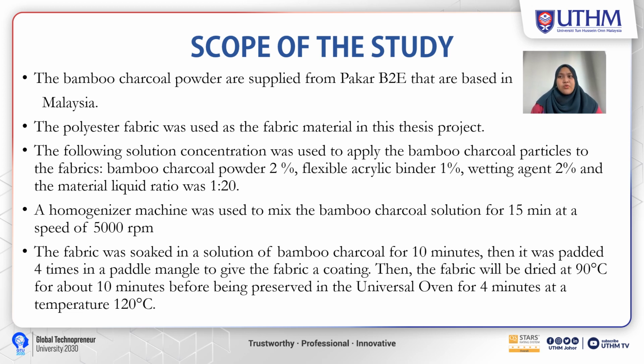The fabric was soaked in a solution of bamboo charcoal for 10 minutes, then it was padded 4 times in a paddle mangle to give the fabric a coating. Then the fabric was dried at 90 degrees Celsius for about 10 minutes before being cured in the universal oven for 4 minutes at a temperature of 120 degrees Celsius.